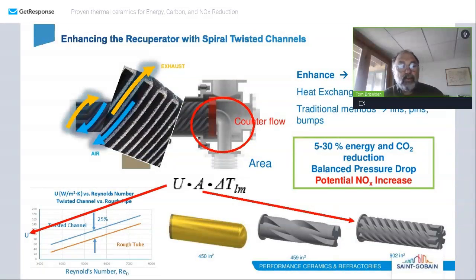A typical recuperator will have a surface area of, let's say, 450. A shallow 3-fin twist design can match this surface area. However, when increasing both the number of twisted channels and the twist rate, a surface area of 2 times is achieved. The corresponding improvement in heat transfer coefficient allows overall radiant tube efficiencies to approach 85%. Thus, 5 to 30% energy and carbon reductions can be realized. The combined reduction of flow rate and improved heat transfer coefficient and counterflow designs allows pressure drop to be minimized in the overall system.